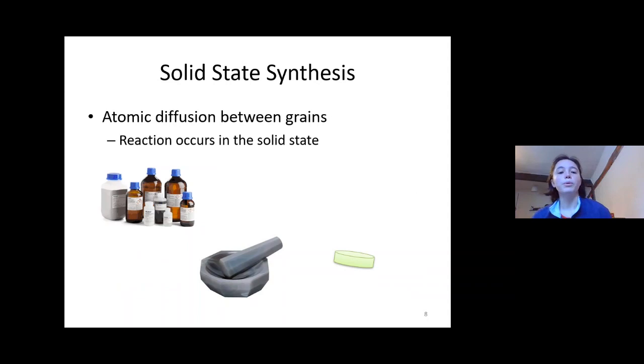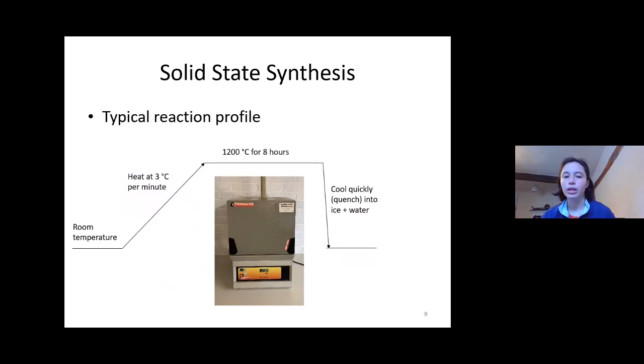And this is also why we want to grind up our samples, our starting materials, into a very fine powder at the beginning, in order to get their surface area as large as possible. We also then press that mixed powder into a pellet. So putting the pressure on it kind of pushes all the grains together and makes them react a bit better. And then a typical thing is we put the sample in a furnace, heat it up slowly, leave it there for a bit, and then cool it down again to take it out of the furnace.